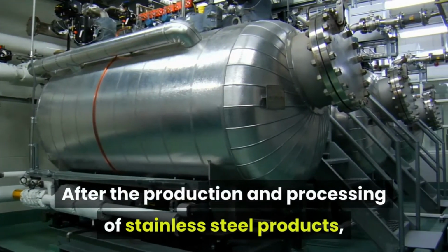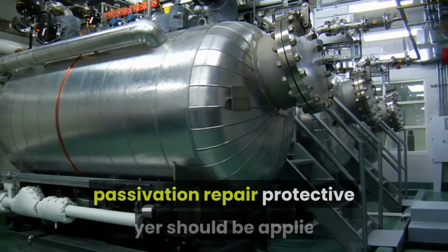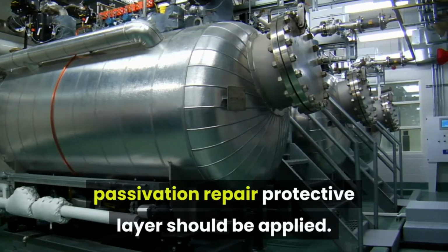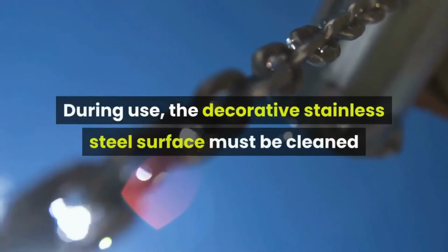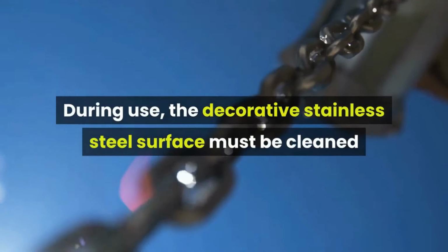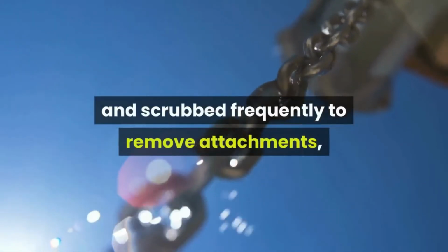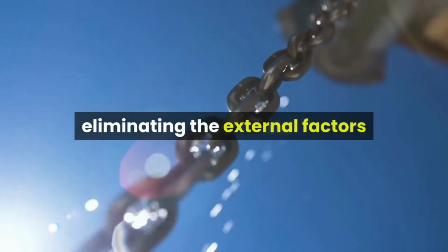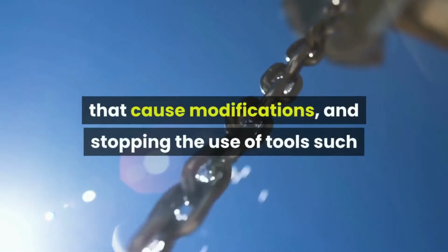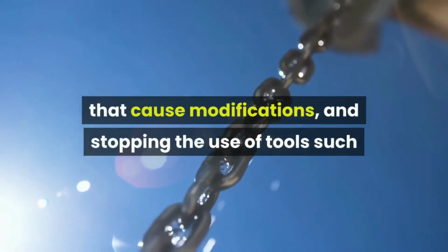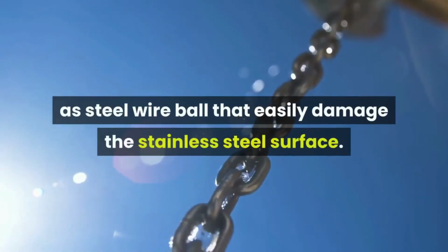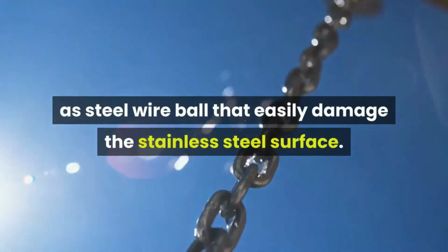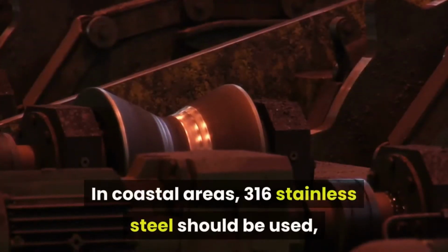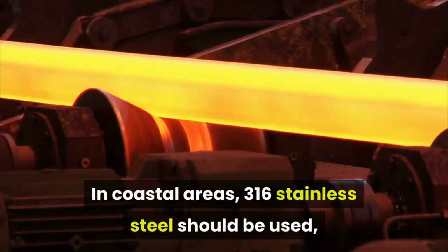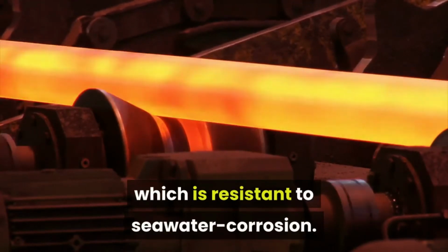Therefore, to ensure that the metal surface is permanently bright and not corroded, we suggest: after the production and processing of stainless steel products, a passivation repair protective layer should be applied. During use, the decorative stainless steel surface must be cleaned and scrubbed frequently to remove attachments, eliminating the external factors that cause corrosion, and stop using tools such as steel wire balls that easily damage the stainless steel surface. In coastal areas, 316 stainless steel should be used, which is resistant to seawater corrosion.